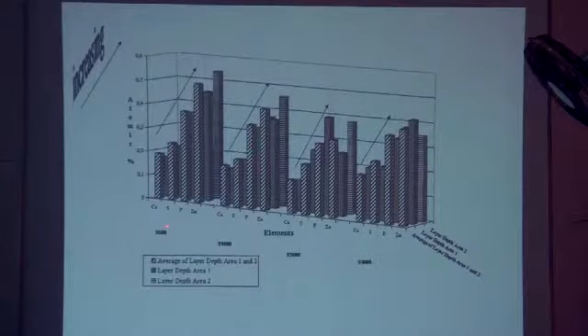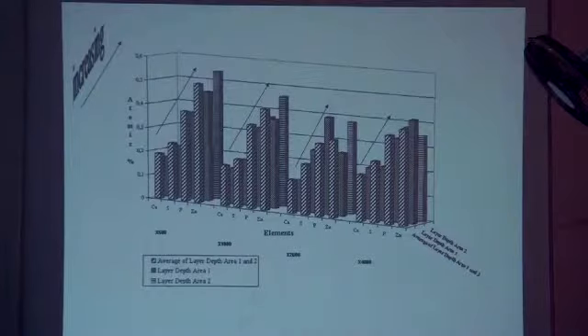We did this from 500 to 4,000 magnification. We found the results, and we ran those tests 3 or 4 times to be sure. So calcium was minimum, then sulfur, phosphorus, and zinc. Zinc was very high, I think because it's the anti-wear agent in the lubricant, protecting against wear.